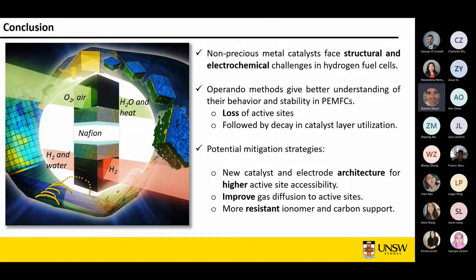Some interesting areas I've seen are making a more resistant ionomer and a more resistant carbon support. What this means is you completely accept that you're going to have iron demetalation, but what if you could make sure that your ionomer is not affected as much because you don't have iron contamination of your ionomer? That's an area that's being looked at. Another area I've seen at the moment is making a more resistant carbon support. There were a few papers recently from groups in the US where they coated the carbon material with a layer of graphene, which makes it more resistant to corrosion, which basically means you accept the problem, you just try to fix it by coating something on top of it.